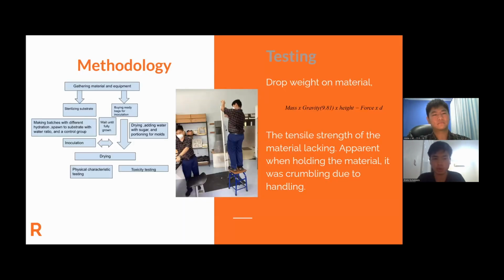Our methodology for this project is, first we gather the material and equipment, after which we start creating the biofoam. In order for that, we bought a bag of substrate and sterilized it. Afterwards, we distribute it across the mold, and we add water and sugar for nutrition for the mycelium to grow. We add the spawn first. It's called inoculation, after which we close the entire product in cling wrap and we poke holes in order for the mycelium to receive oxygen from outside.